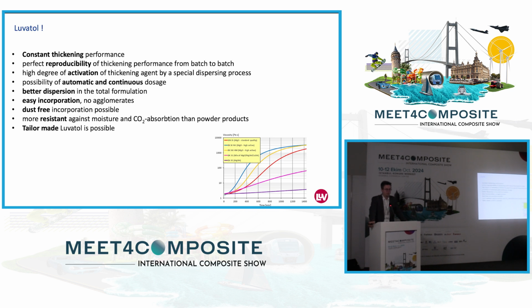You have, of course, a better dispersion because it's easier to enter a liquid in a liquid instead of lots of powders. It's dust-free, and it's more resistant against moisture, especially some parts where we put, for example, moisture absorbers in there. But on the other side, it's not like the ultimate goal you can get, which solves all your problems. Of course, there are lots of things you need to consider when you test or want to change from powder to a paste, when you want to use Luvatol. Some are pretty obvious, and some are not so easy to identify.